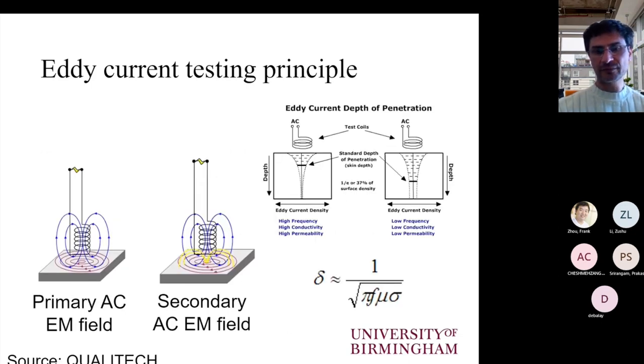This is a set of schematic diagrams that shows the eddy-current testing principles. As I said earlier, in the most basic scenario, we have a coil which is fed with an AC current. This generates an AC electromagnetic field, which when it is near a conductor will cause eddy currents to flow close to the surface of the conductor. These eddy currents will result in a secondary electromagnetic field to be generated, and of course that will change the impedance of the coil. If we have the presence of a defect, the flow of the eddy currents will be disrupted, and that means that the secondary electromagnetic field will also be changing in shape and magnitude, and that will give rise to changes in impedance.